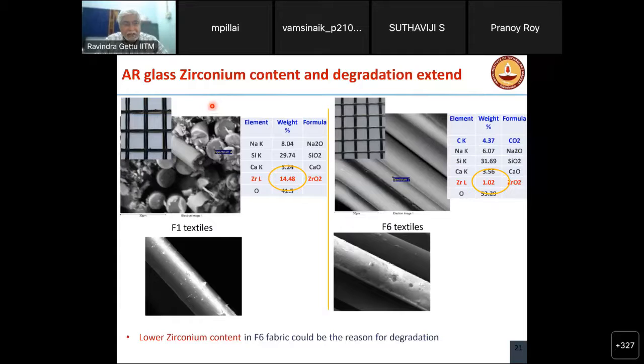Also, when we are talking about AR glass, there are a lot of alkali resistant glass in the Indian market, which really are not alkali resistant. There are many people who are selling what they call alkali resistant textile, which is not true. The true alkali resistant glass has to have zirconium. It has to have about 10 to 15% of zirconium, but there are others in the market which have almost nothing. We have found some which only have zirconium in the surface or very low zirconium content. And when we analyze this, you see this pitfall.